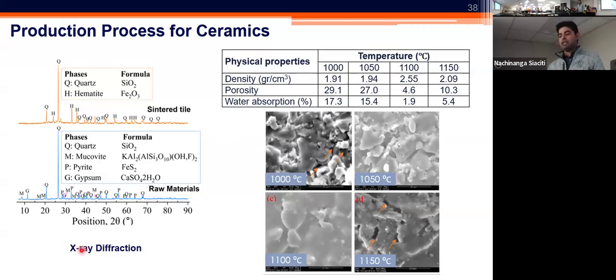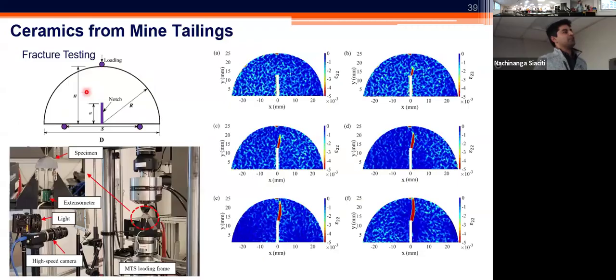We also confirmed through the X-ray diffraction evaluation that the raw materials, in fact, the muscovite, pyrite, and the gypsum, were all transformed into a new phase known as hematite through this sintering step. So they were no longer present in the original form, and hematite was formed in addition to the quartz for all these materials. We were also interested in evaluating, in addition to the strength, the fracture behavior of these materials. So we did fracture testing, again, using semicircular bend geometry, and confirmed the fracture toughness for these materials and looked into the size of the fracturing.